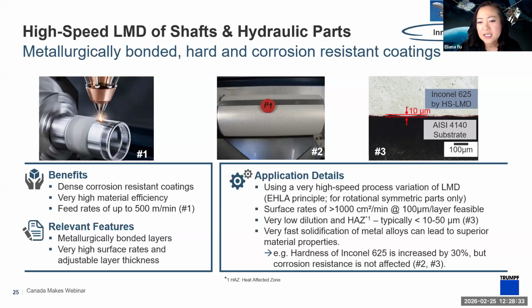This is what we call the EHLA principle. So there's extreme high-speed laser application or laser cladding, you'll see it's called, which is used a lot for repair in brake pads and things like that in the automotive world, but also can be used for anything that has a friction or wear resistant requirement added. So this one, for example, is adding 625, which is a nickel alloy, using this high-speed layer onto a substrate of a stainless steel, and very good coating result. So very low dilution and small heat affected zone. So that's all good news.